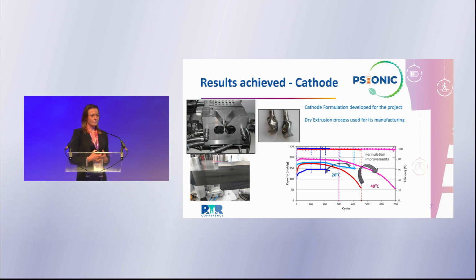So the challenge after was to boost the performances of the cathode part, and this was done, as you can see on the slides. The first results were the red and dark blue ones, and we've tried to improve the performances, and now we get the pink and the light blue ones. So we already get very good cyclabilities at 40 degrees, and we still need to improve it at 20 degrees, but it's ongoing.